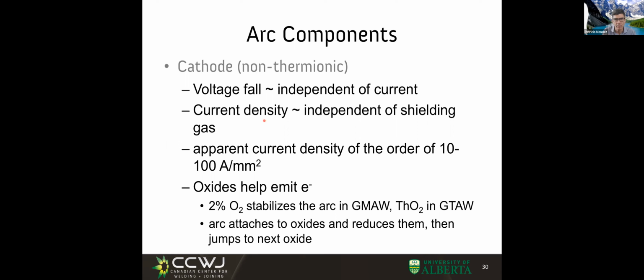And these little local mini cathodes, right? They attach to things that would have higher facility to emit an electron. For example, oxides, right? Oxides help emit electrons, and that's the reason we use, for example, 2% oxygen to stabilize the cathode in steel welding, because this little amount of oxygen is going to create some amount of oxidation that stabilizes the cathode, right? This is the reason why, for example, if we put thoria in TIG, the fact that it's an oxide helps lower the work function of the tungsten electrode and help it be more stable and colder, right?